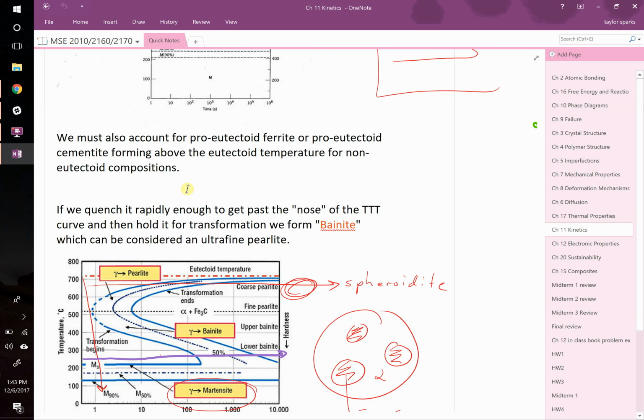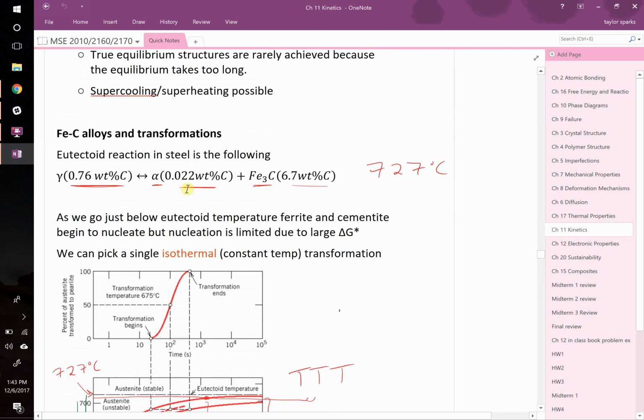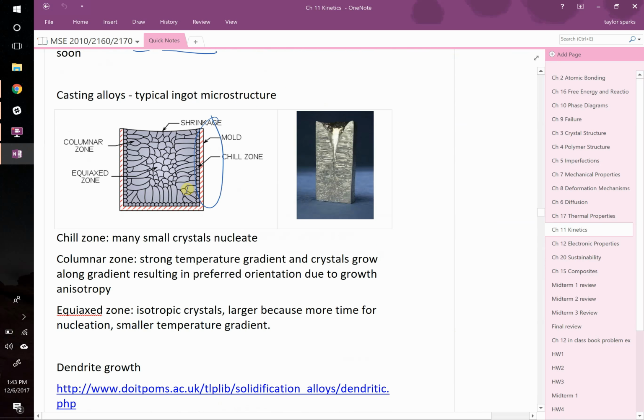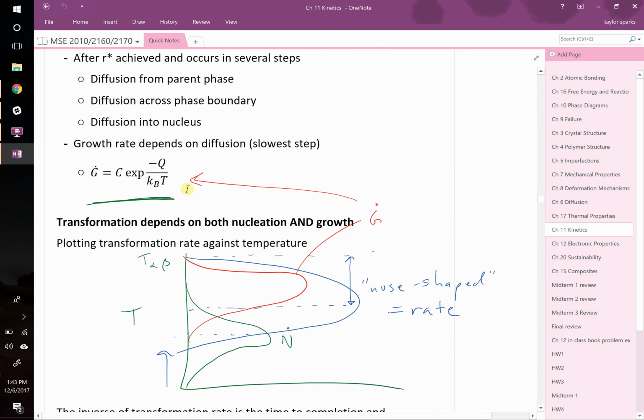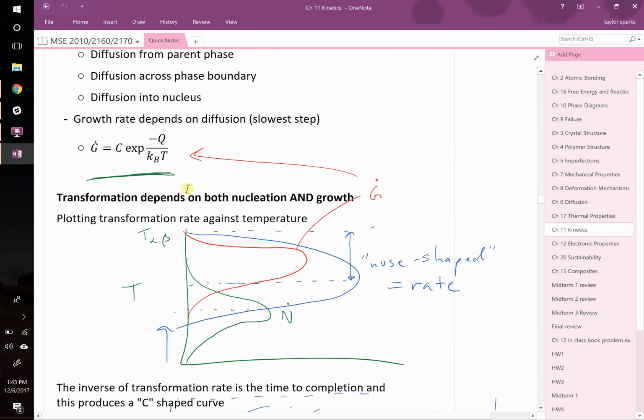Why is there a nose? Yeah, we can explain that. It goes back to the earlier part of this chapter in kinetics when we said that transformation depends on a couple things. It depends on the nucleation rate and your diffusion rate. Those two things together give you transformation. Right? It's not enough just to nucleate things. Your phase has to nucleate and then grow.